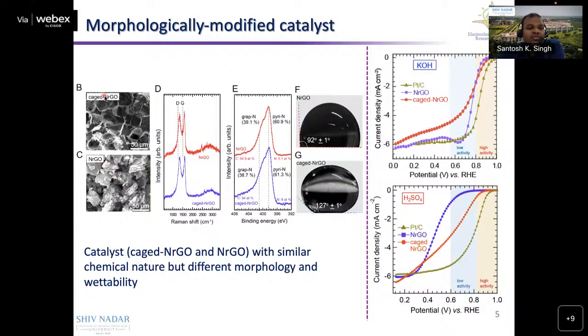nature. However, we have also prepared one by following the soft template method, which has cage structures. These cages are a porous structure, which creates surface tension in the water molecules, and that creates hydrophobicity. Both materials were synthesized by following a similar method and similar conditions, so that the chemical composition of the catalysts should not change.